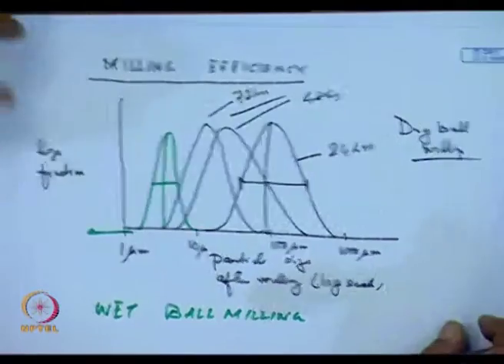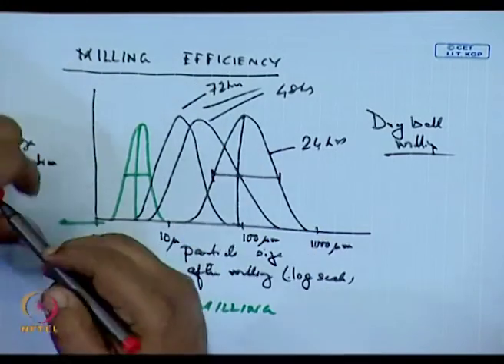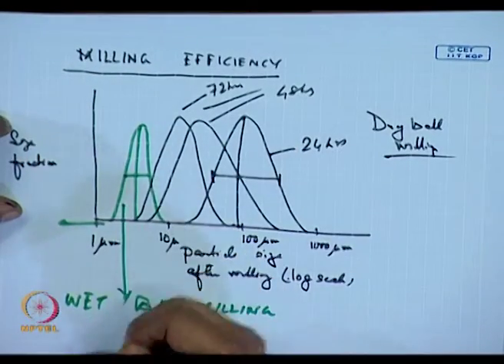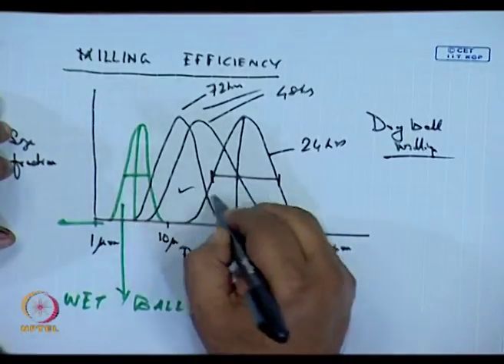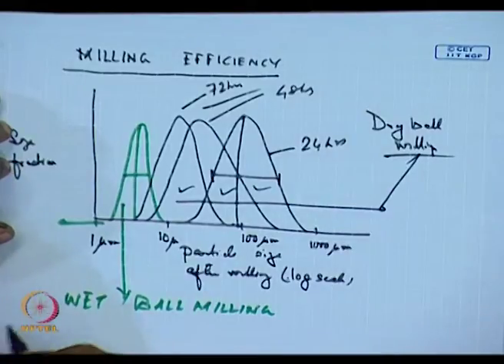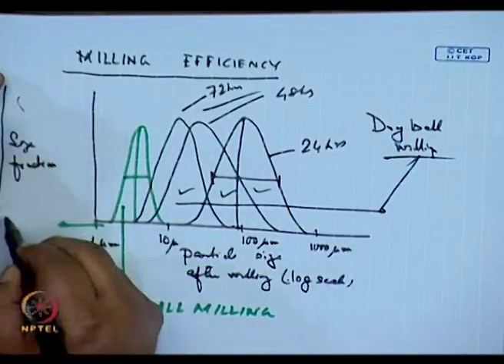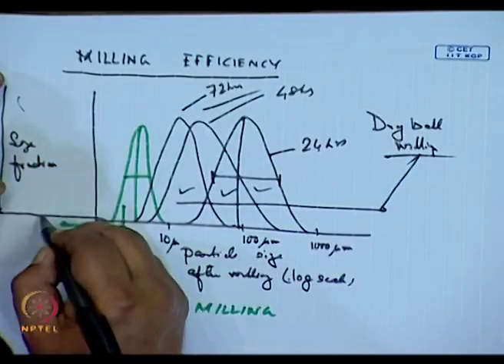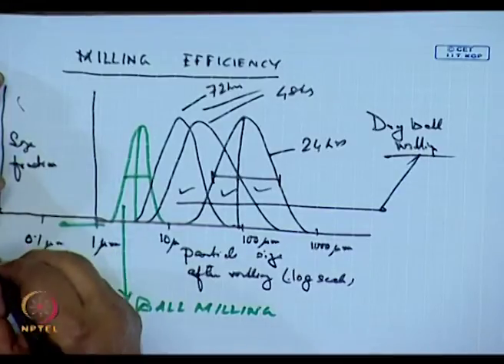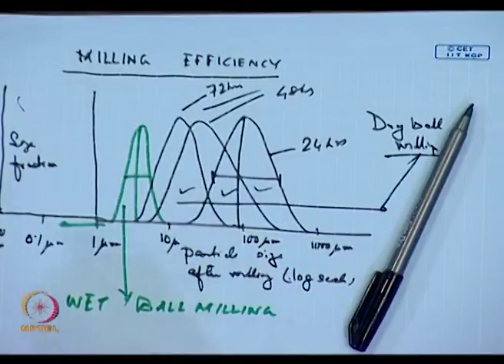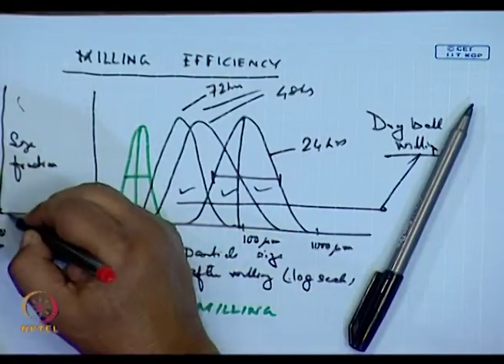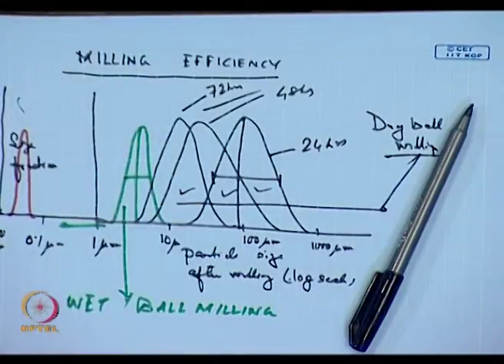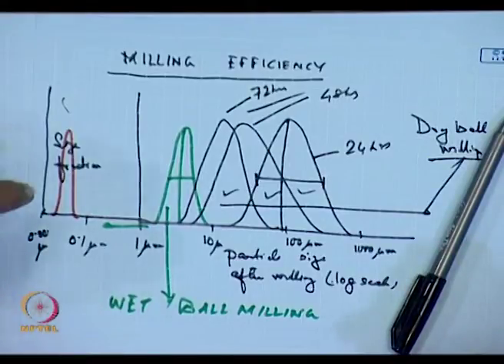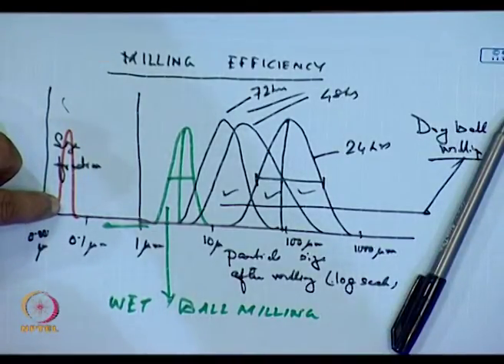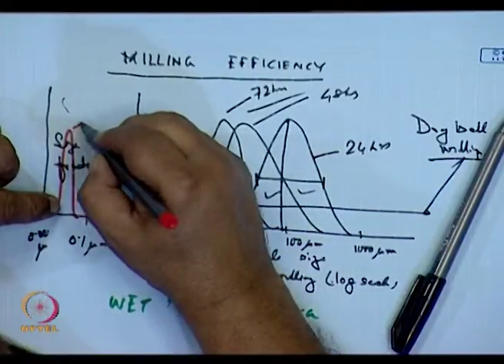The particle size distribution here, if I use this diagram: this one was for wet ball milling, and these three were for dry ball milling. If on the same scale I draw for the attrition ball mill, this is down to 0.1 micron and this is 0.001 micron. With an attrition ball mill, particle sizes in this range are routine. That is, submicron particle sizes are routinely available with an attrition ball mill.